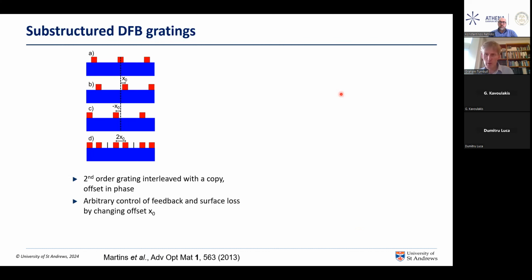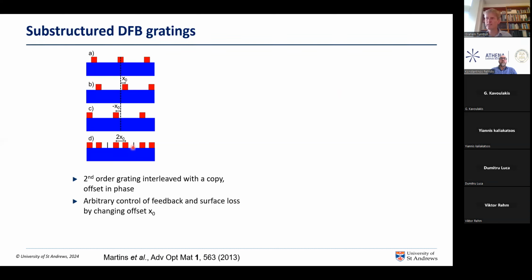There's another approach that we have settled on as our preferred way to make very low threshold feedback structures, and that's to use what we call a substructured grating. And so here we take a second order grating, which is a surface emitting structure, and we essentially make two replicas shown by lines B and C, which are slightly offset in position from each other, so that we end up with a periodic structure that has two teeth in every unit cell.